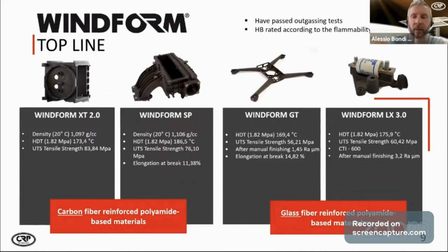We have many customers which are doing drones. You can see the characteristic, the features of a little bit lower HDT compared to the other 2. UTS as well is 56, but the main feature is elongation at break, which is 14.82, and very good manual and very good surface finishing, it's 1.45.